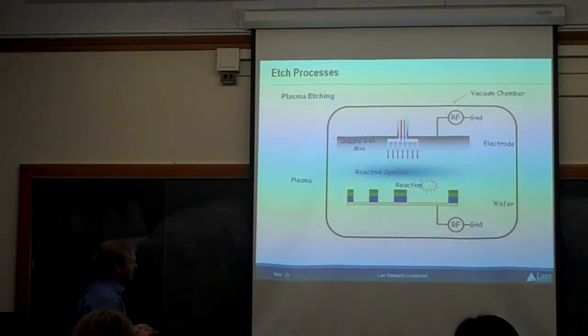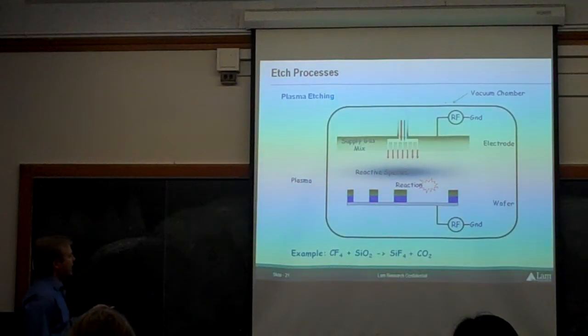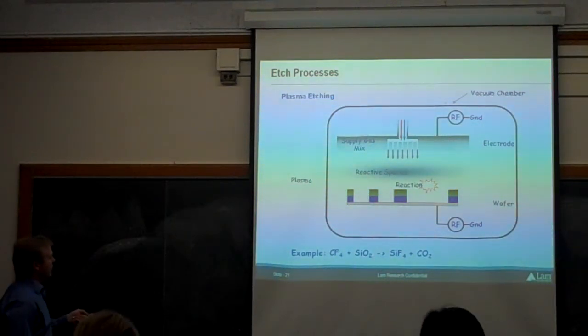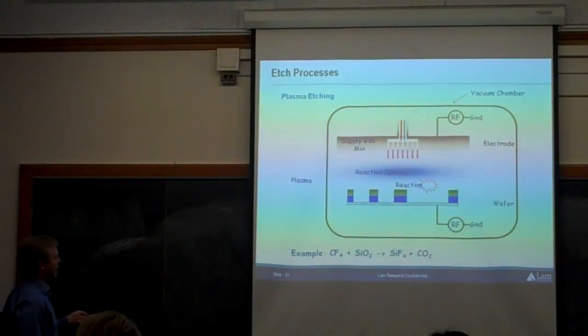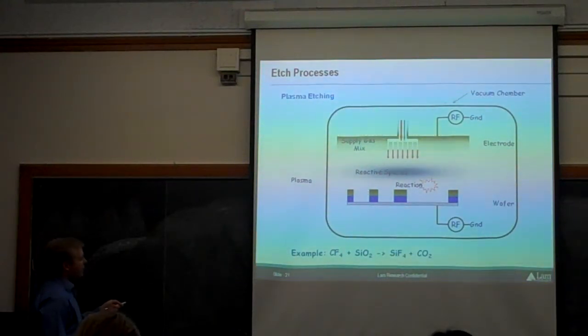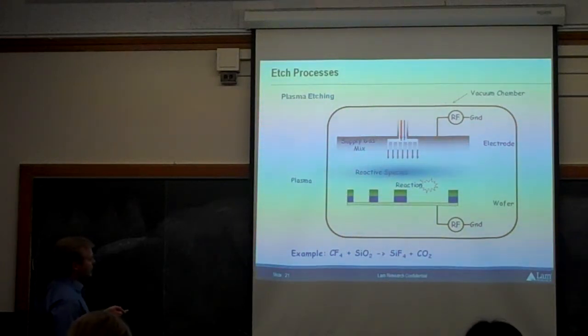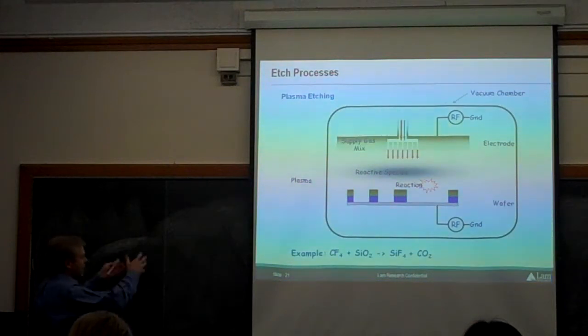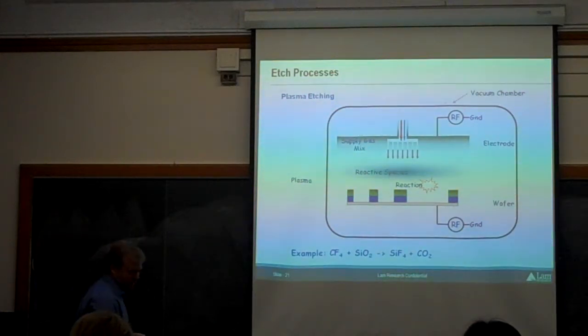So the blue goes away, or the purple. And in this case, if this purple layer was silicon dioxide, I could put in carbon tetrafluoride and form volatile byproducts, both CO2 and SiF4, that will get pumped away. So we've got, again, a vacuum chamber, and those byproducts go away, and everything's great.